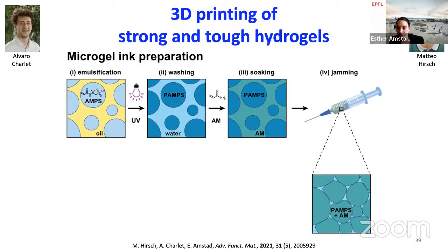And I have two very talented PhD students who had a very good idea. They thought, well, let's go a step back. Instead of using these capsules, let's use simpler microparticles, the hydrogel-based microparticles. Each hydrogel has a sponge-like property because it's a polymer network that is filled with a very high fraction of water. Now, if we load them, instead of just pure water, with water containing some reagents, we can store a lot of reagents within these particles. So they made these hydrogels, incubated them in an aqueous solution containing their reagents, and then they jammed them.